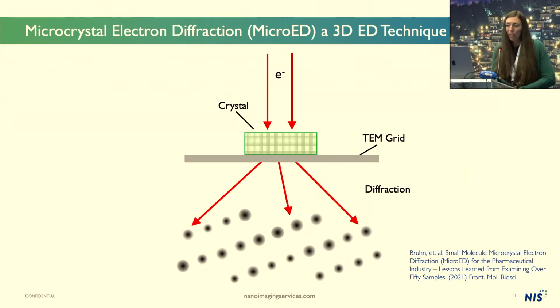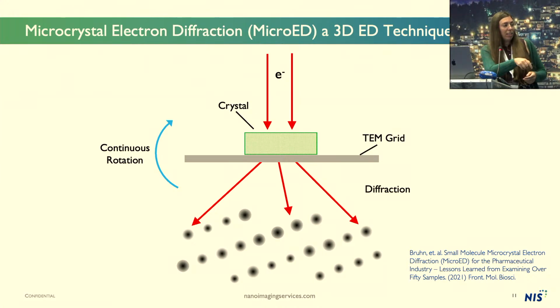All right, so a little bit about how the technique works. It's very analogous to other diffraction experiments that you're used to. You have a radiation source, in our case it's electrons, and crystals, which in our case we have placed on a flat TEM grid surface, transmission electron grid. And when we expose these crystals to the beam, we'll get a diffraction pattern like you're used to seeing. And when we couple this with continuous rotation of the stage, we can collect data in a manner that's analogous to the way that most single crystal X-ray data is collected.